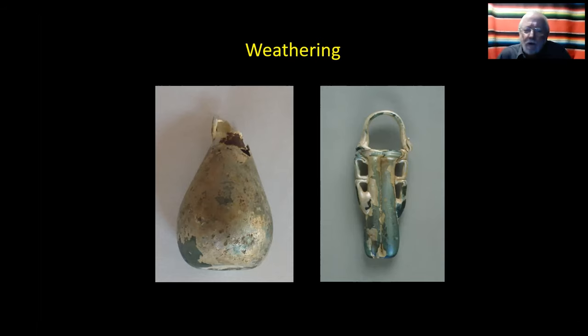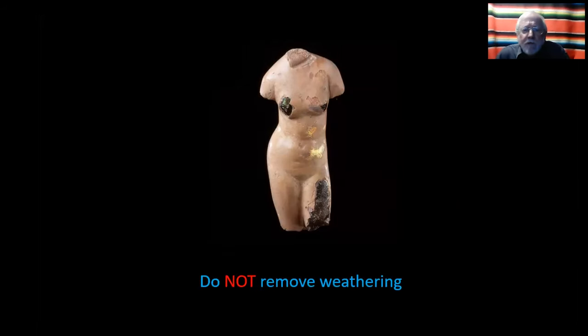We don't remove the weathering. It used to be removed routinely by archaeologists because they wanted to see the color of the glass. But we really don't do this anymore. And this is a good example why. So here you have an Aphrodite, again, from the Corning Museum of Glass collection. It's developed very thick weathering layers over a long period of burial, probably again, just over 2000 years or close to that. And whoever found it, or whether it was illegally excavated or not, we don't know, but they scraped off some of the weathering to look at the color of the glass. And as you can see, it's kind of a transparent purple. And so it's changed, it's altered quite a bit in its weathering. And you can see even in the belly, you've got some iridescent showing up underneath this layer that we call opalescent. And the opalescence is fairly obvious because it looks like an opal.